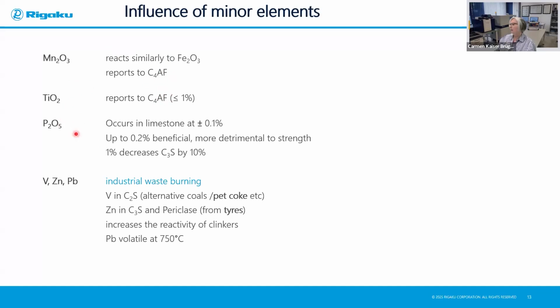Yes, the P2O5, which naturally occurs in limestone, can be beneficial but is more detrimental to strength. Every 1% can decrease the C3S by 10%. So we have to control these minor elements very precisely. And most importantly, industrial waste has a lot of influence, because heavy elements like vanadium and zinc, which are transition elements, or even lead, which is a heavier element, can influence these phases that we get in the clinker.